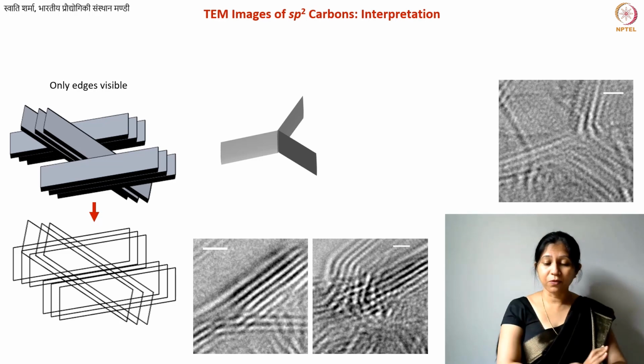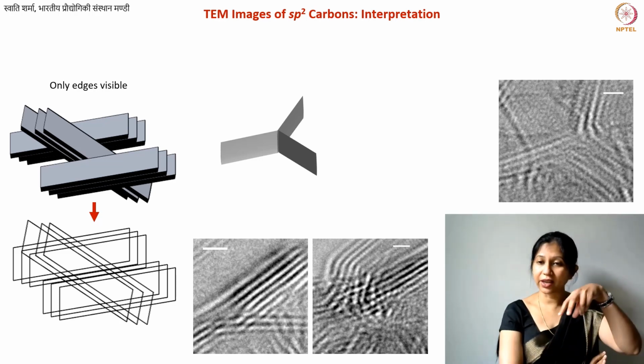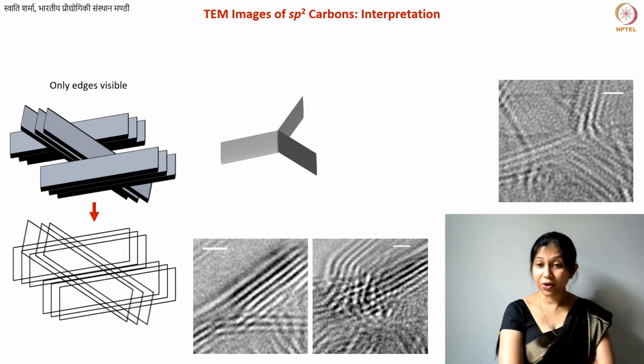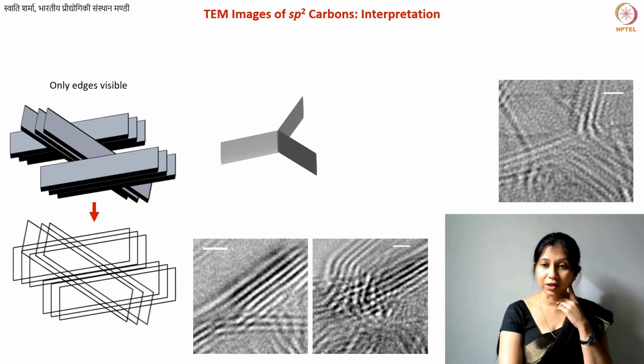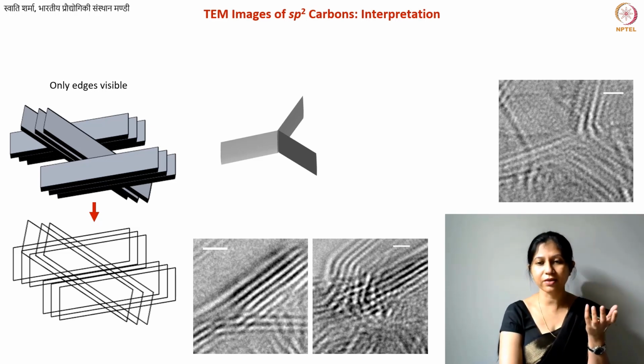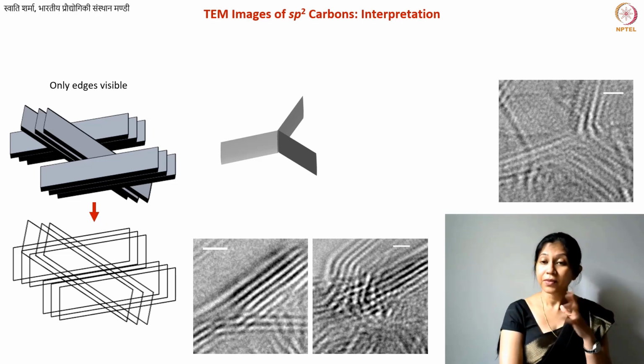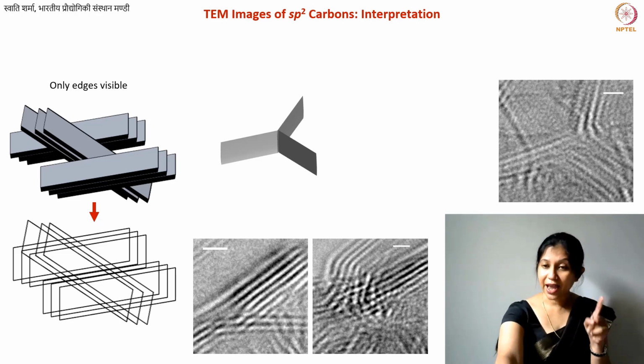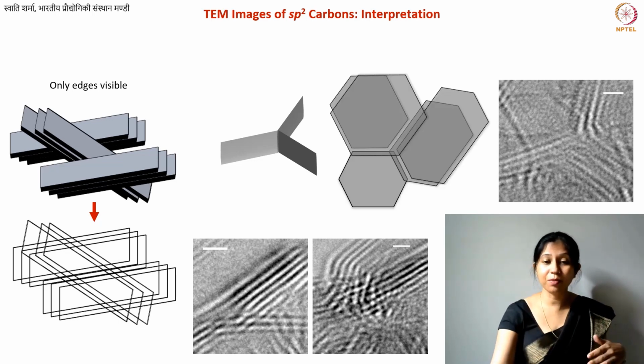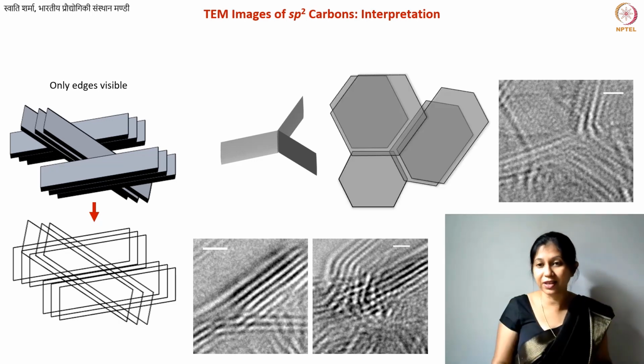You have these triangular junctions that are definitely present in sp2 type carbons, right? They have 120 degree angles, and they are present. And if you read some of the very old books and so on, there has been a reasonable description of these kind of structures as well. So when I saw this, I was really happy that I saw this triangular junction. But while it can be this kind of junction, it can also be just the top view of these various hexagons.